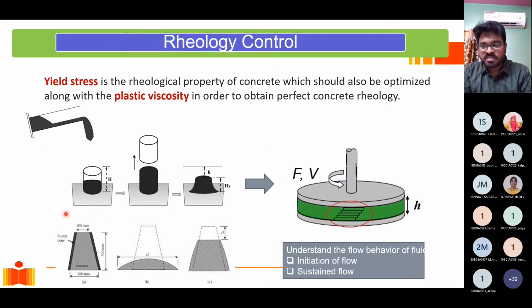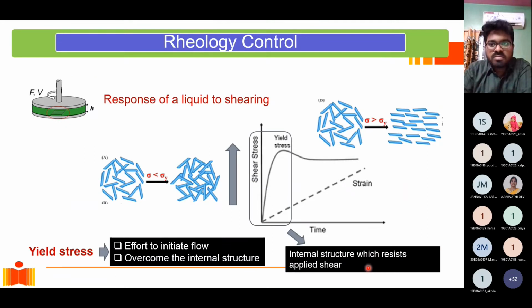So this gets into rheology control. We need to understand what rheology is, and we have to understand what fluids are, because this takes us out of the solid domain. We need to understand fluid behavior, what happens when you apply shear to a liquid. Whenever we have a viscous or thick liquid, we measure flow in terms of slump. We fill a container, lift it, and measure how much the material has slumped. We can get either a flow or a slump behavior, depending upon how the material behaves under shear. This is about understanding what it takes to initiate flow and what it takes to sustain it. We are beginning to understand that these materials are very complex in nature.